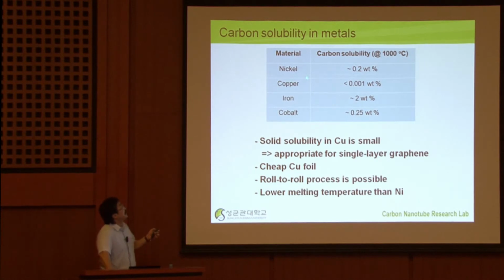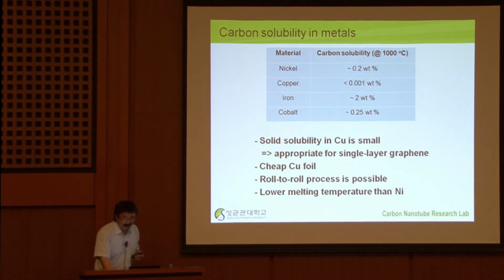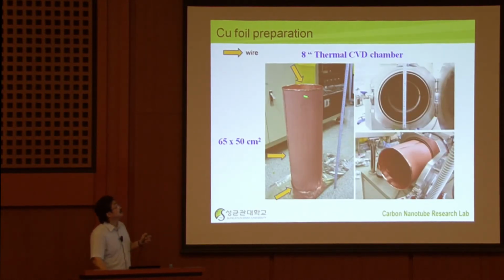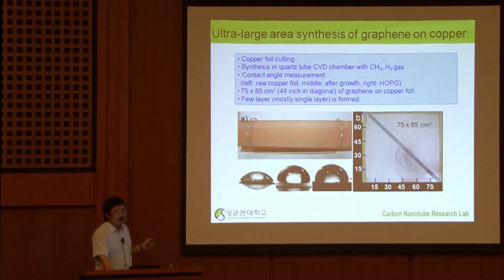But if you look at copper, copper has very low carbon solubility. Of course, there is no guarantee that you will get a single layer. But somehow, by chance, if you use copper, this is a perfect condition for having single layer graphene. Actually, everyone can succeed in this. For instance, you can simply have this copper foil, large area, roll it up and insert it into this quartz chamber. And you simply supply the hydrocarbon gases at high temperature, and you will get graphene formation on the surface of this copper film. So this is how we get large area graphene.